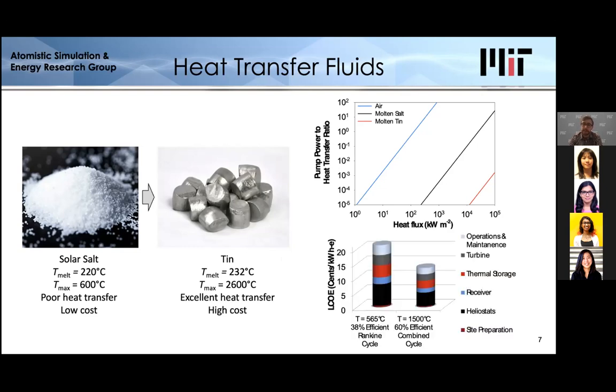Additionally, the higher temperature allows us to operate a much more efficient combined cycle compared to the Rankine cycle, which is typically used at these plants. So by switching from a maximum temperature of around 565 C, which is limited by these solar salts, to a maximum temperature of around 1500 C, which is now limited by the heat engine itself, or the conversion system itself. That's the maximum temperature for that. So we're no longer limited by our fluid.